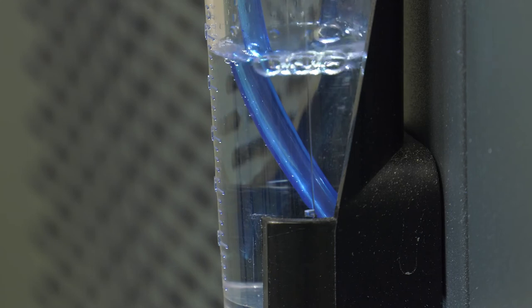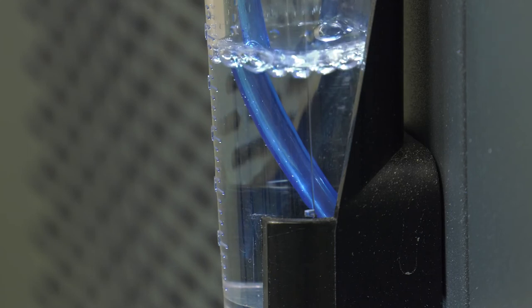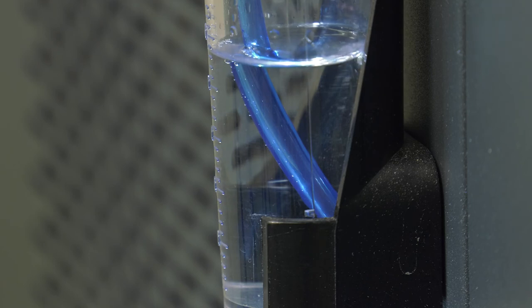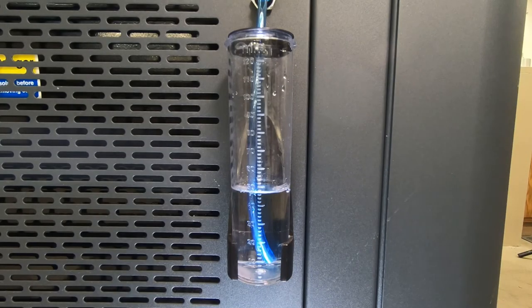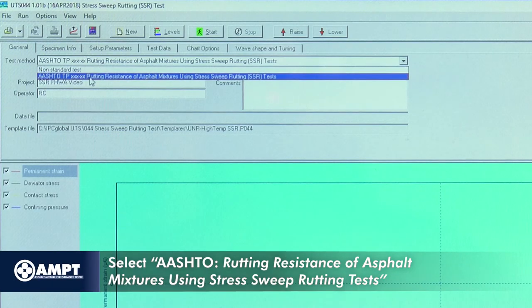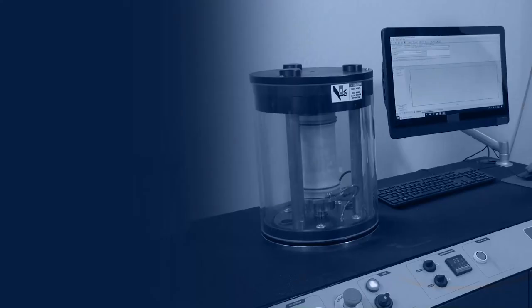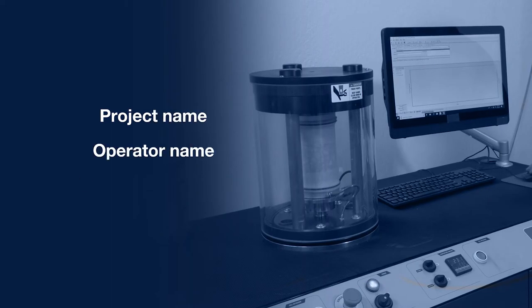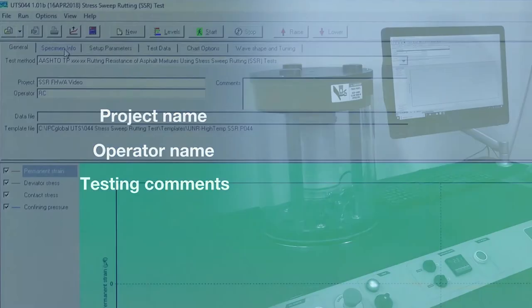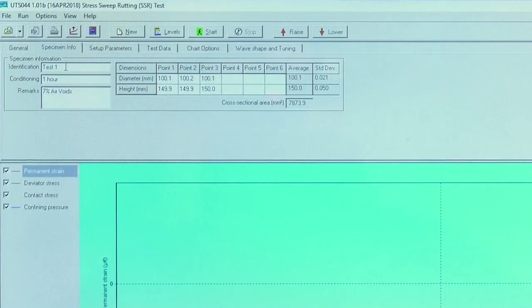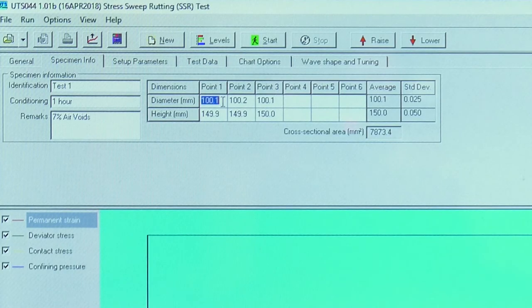Watch the bubble chamber to ensure air comes through the drainage line. Check the air bubbles for 10 to 15 seconds. A frequency of approximately 1 to 10 bubbles per second indicates proper drainage. No bubbles may indicate a blockage, and a faster rate may indicate membrane leakage. Under the General tab, select AASHTO Rutting Resistance of Asphalt Mixtures Using Stress Sweep Rutting Tests. Enter project name, operator, as well as any testing comments. Under the Specimen Info tab, enter specimen identification, conditioning time, percent air void, and diameter and height of the specimen.